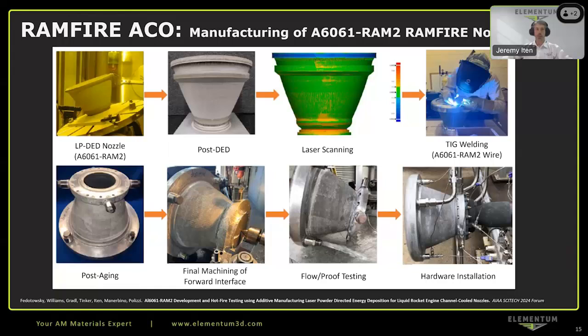Here's the steps for the manufacturing of the A6061 RAM2 RAMFIRE nozzles. So on the upper left, you can see the laser powder DED nozzle being produced. After the production, you can see the nozzle there in the second image. The part was laser scanned to confirm that the geometry was correct according to the CAD model. And then there was TIG welding to weld a wrought produced manifold structure to that chamber. The manifold could have been printed directly on there, but it's basically a big bulky piece of metal, and it was more cost effective to produce that through other processes.